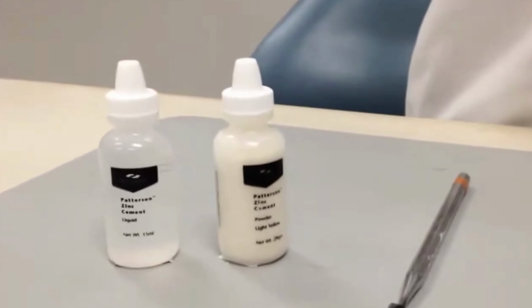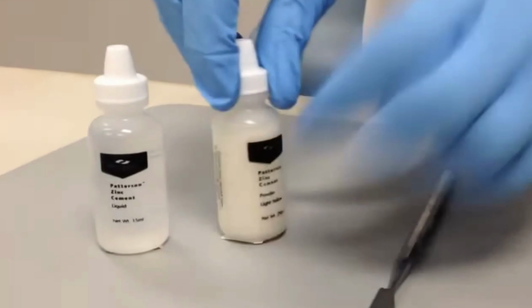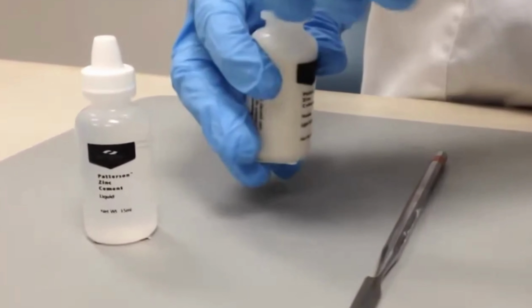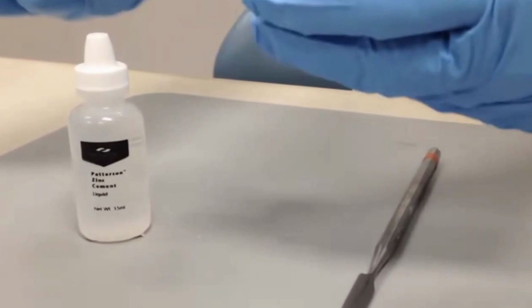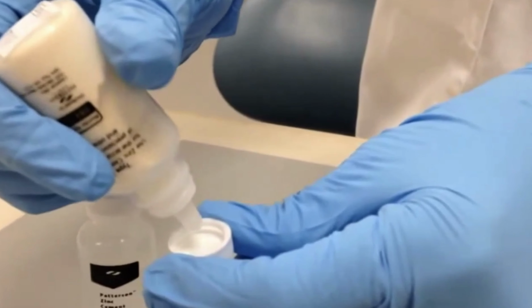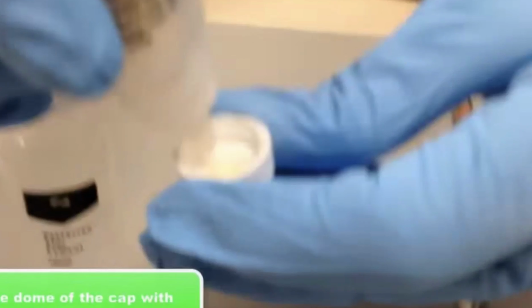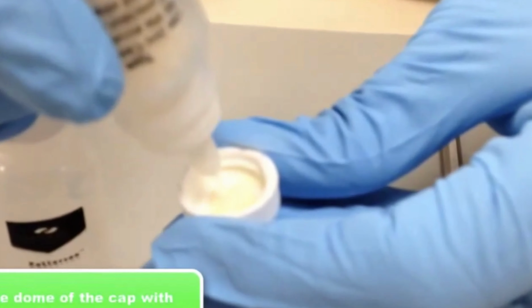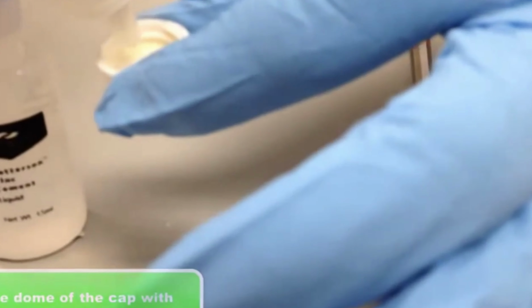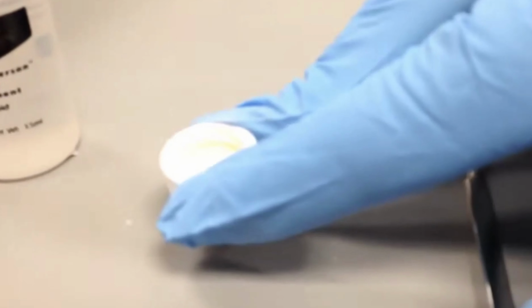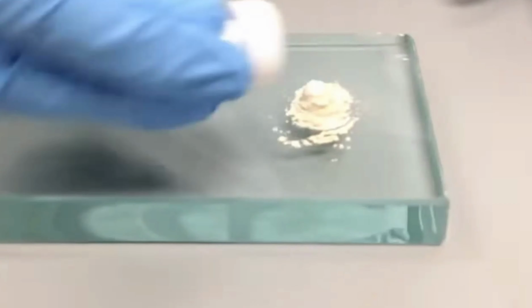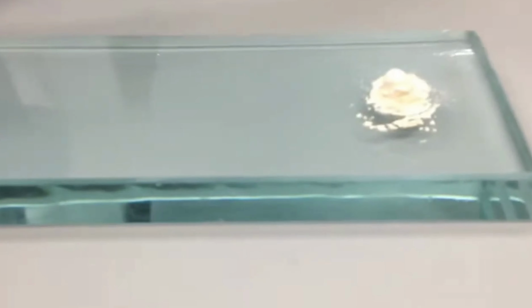This video will demonstrate the process of mixing zinc phosphate cement. We'll see two examples of the procedure for mixing zinc phosphate cement. One is luting and the other one is for a base. So the first step is to fill the cap up to the dome line with powder. She's just tapping down to level it out. Okay. And then as soon as you get that, you pour it onto the glass slab that's been chilled.